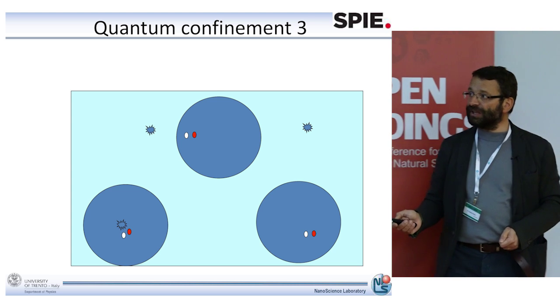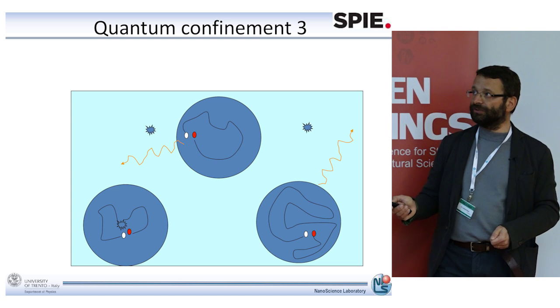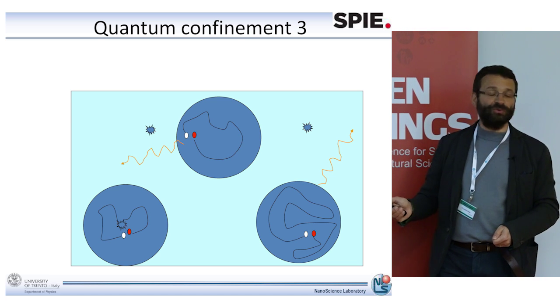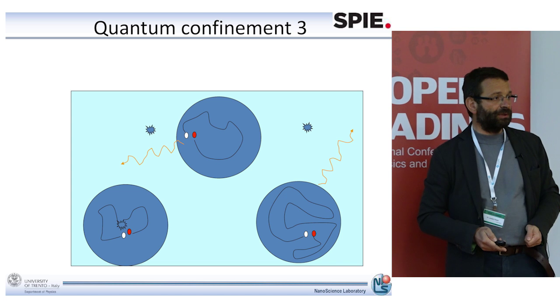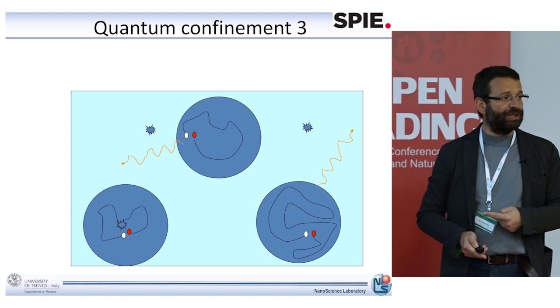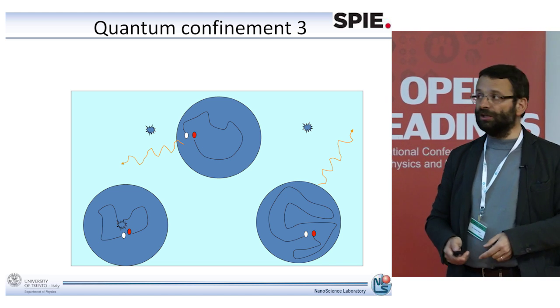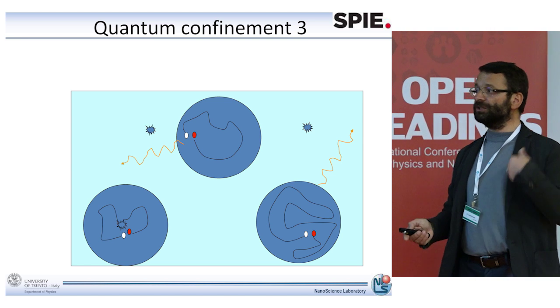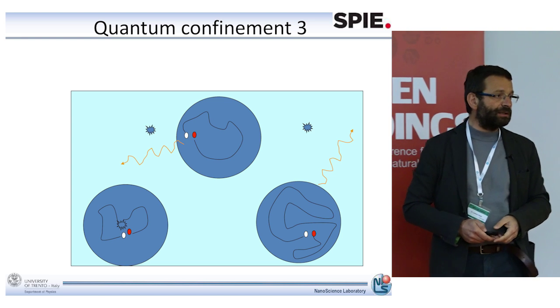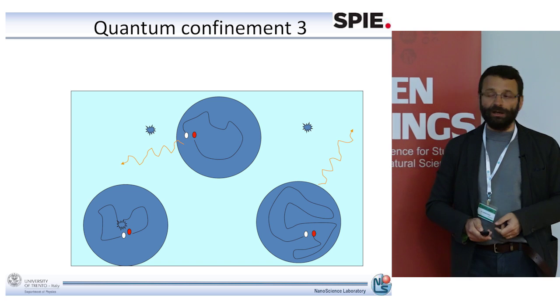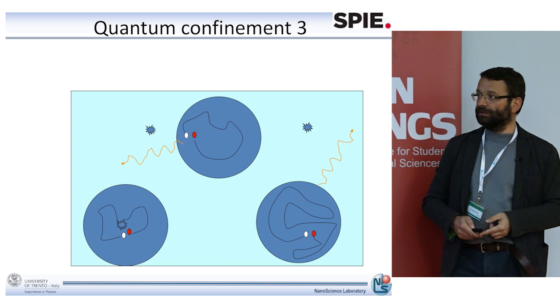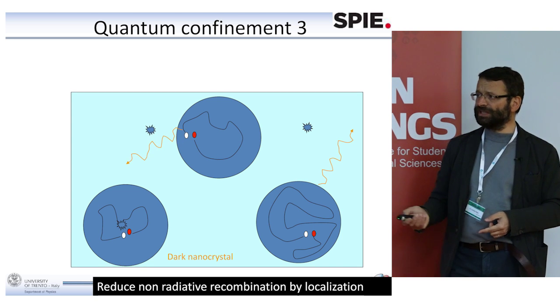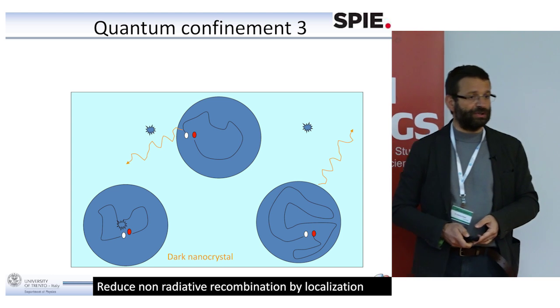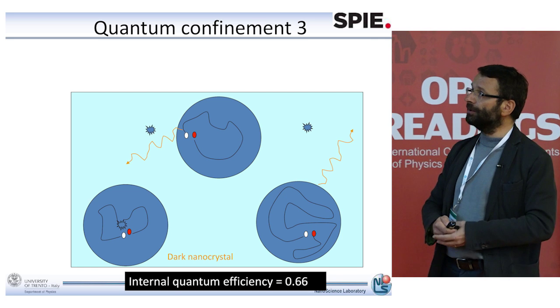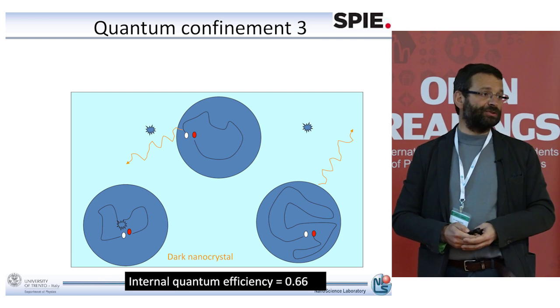So now in this example, I have excited 3 electron-hole pairs, and I get 2 photons out. That means that this system has a very high internal quantum efficiency because of the reduced non-radiative recombination caused by localization of the electron-hole pairs. So the example here is of a system that has an internal quantum efficiency of 66%. Good. How do we make those nanocrystals?